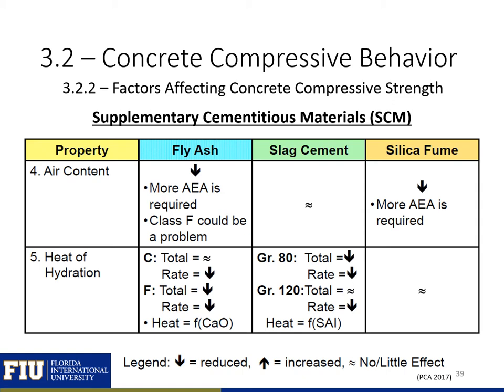The pozzolanic reactions resulting from the use of fly ash occur after the hydraulic reactions of the Portland cement. Typically, enough Portland cement is replaced by fly ash to decrease this initial heat of hydration. Slag has a higher C2S content than Portland cement. Since C2S is slower to react, the initial heat of hydration is lower.